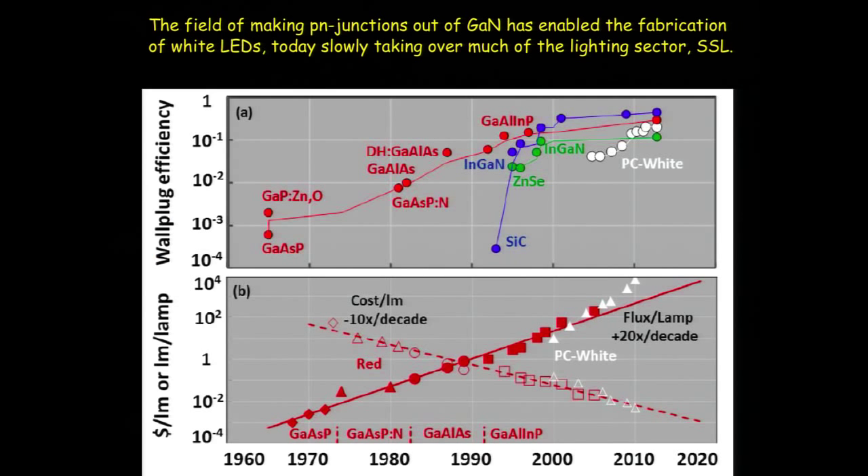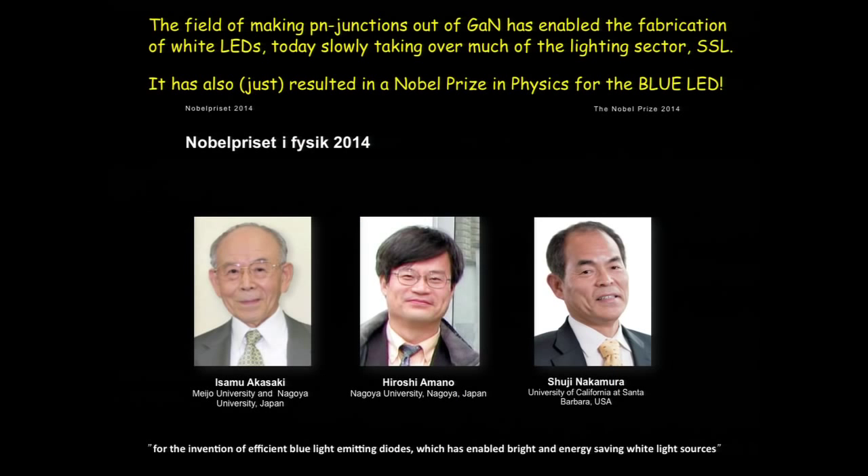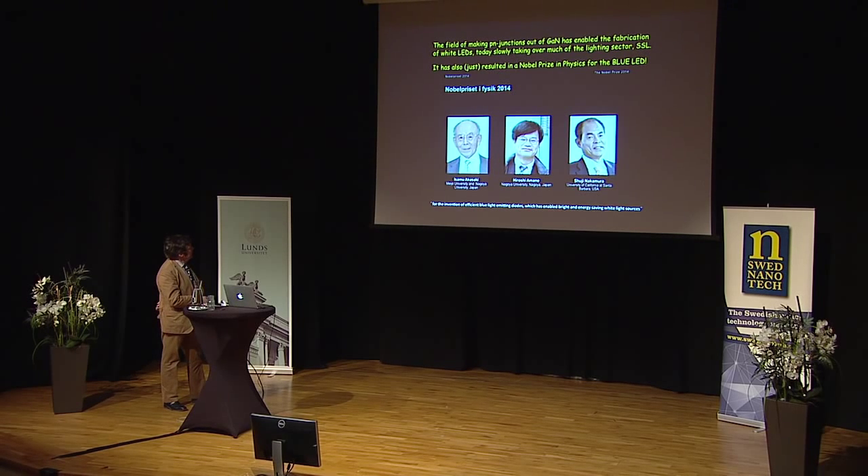On the green, it's much more complicated — indium gallium nitride LEDs are now a little more than 10% efficient, and that's one area where we really have to do something. The white circles here are the phosphor-converted white LEDs, where an efficient blue pumps a broad spectrum of phosphor that creates a broad spectrum appearing white, but with its limitations. These are the three laureates who will come to Stockholm in December, celebrated for the invention of the efficient blue light-emitting diode, which has enabled bright and energy-saving white light sources.